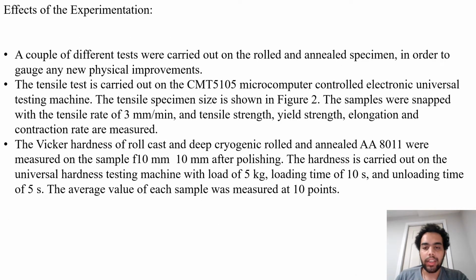And what are the effects of the experimentation? A couple of different tests were carried out to measure what was different before the rolling and annealing and after rolling and annealing on the aluminum. These were done to gauge the tensile strength and the hardness. The tensile test is carried out by the CMT5105 microcomputer controlled electronic universal testing machine. The tensile specimen is shown in figure 2. The sample was pulled at a tensile rate of 3 mm per minute, and tensile strength, yield strength, elongation, and contraction were measured. The Vickers hardness of roll cast and deep cryogenic rolled and annealed aluminum was measured on a 10 mm sample after polishing.